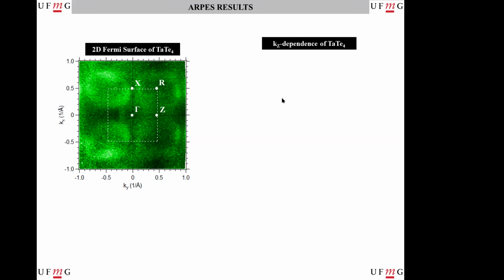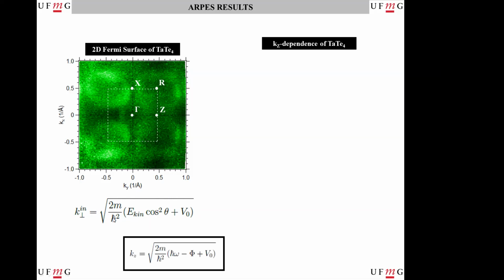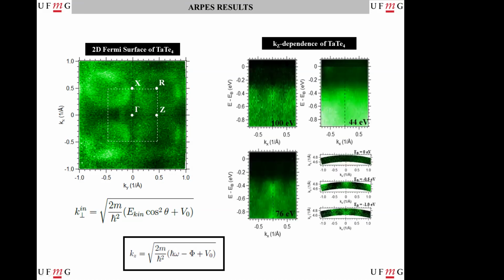Another thing that we did on this sample is what we call the Kz dependence. We know that the momentum perpendicular to the sample is not conserved, and it depends on this quantity here. When we go to a position on the sample where this angle theta is 0, which is the gamma position, what we call the normal emission, this number is equal to 0, and we can have a direct relation of the Kz momentum with the photon energy. And that's what we did.